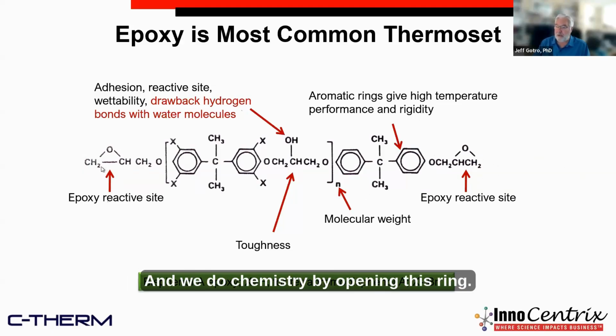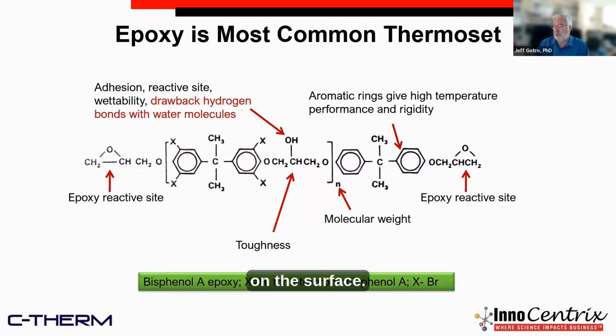And we do chemistry by opening this ring. And it has this OH group in the middle. When you open up one of these rings, you form another OH group. The OH group is good for adhesion. It's a reactive site, so it can do chemistry. It helps when you're putting it down on the surface to wet the surface to get good adhesion.